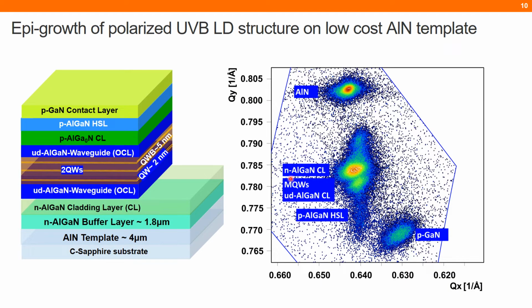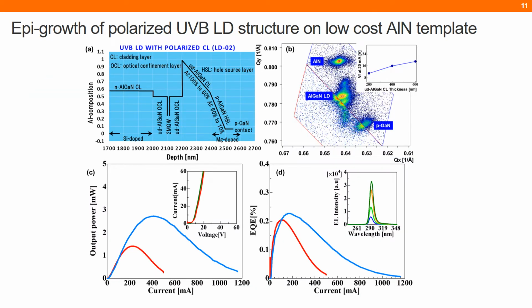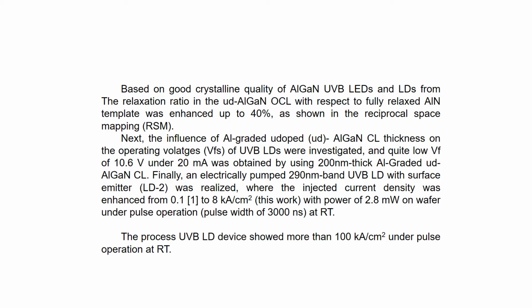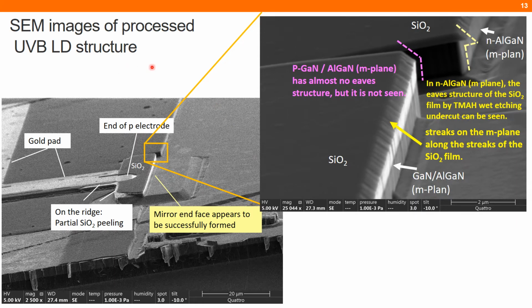These grown structures were used to make the ridge structure. Here is the SEM image of the processed UVB LD structure. You can see the end of the P electrode here. This is SiO2 covering this part, and here is the mirror structure. On the ridge, the partial SiO2 peeling was a problem, but later we resolved this problem.